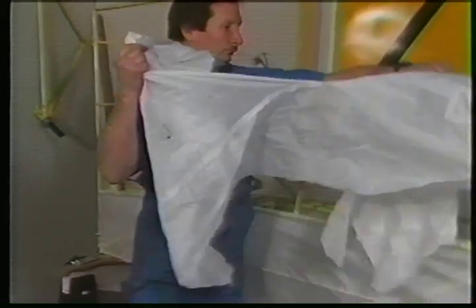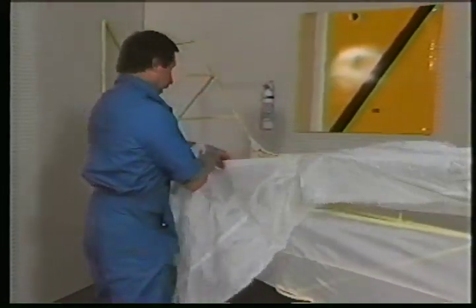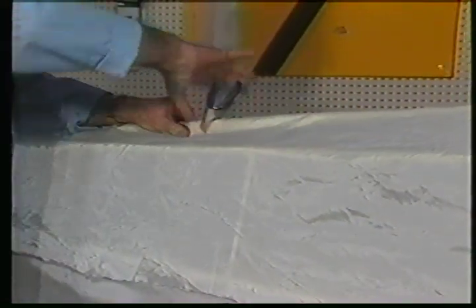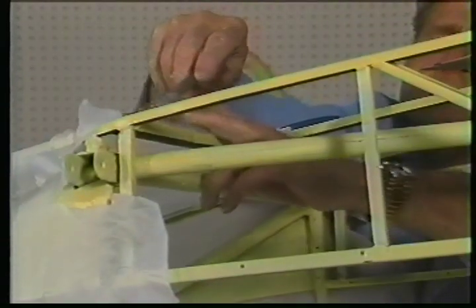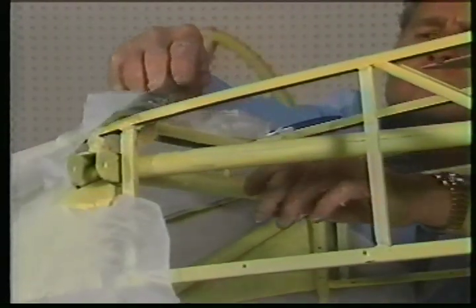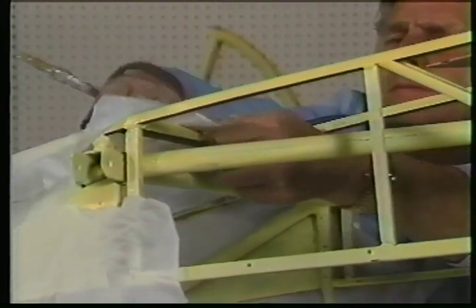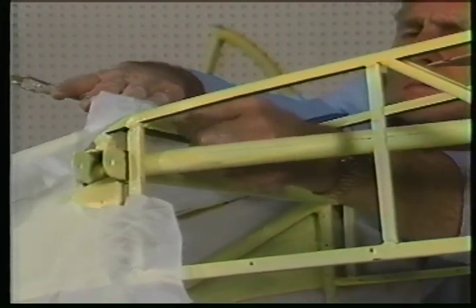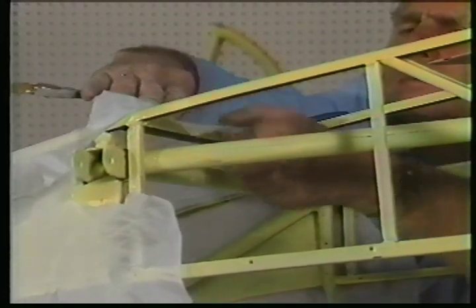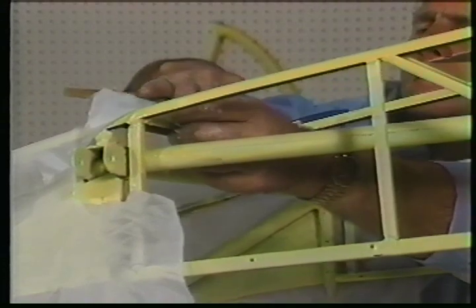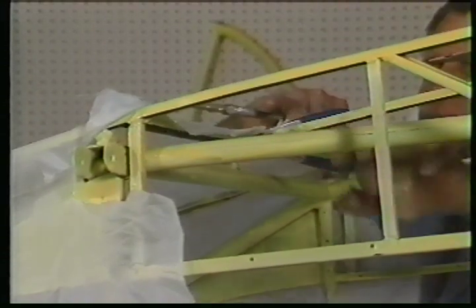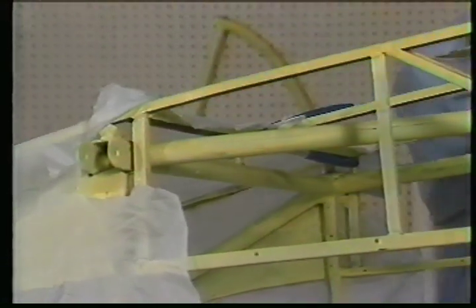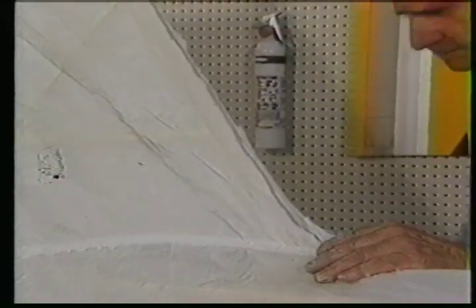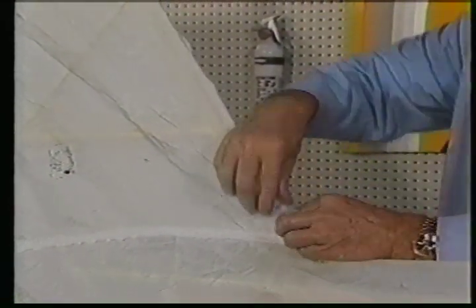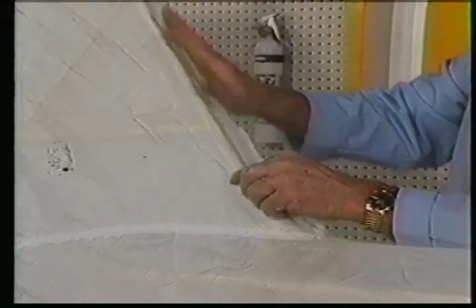After the machine sewing is completed, the top section is positioned on the fuselage and held in place with spring clamps. Start cementing at the top of the fuselage aft of the skylight with the overhang long enough to wrap 270 degrees around the C-section. Special attention should be given to duplicating the original manufacturer's technique of attaching the fabric around a skylight on a high-wing cabin aircraft. Next, trim and fit the overlap seam on the front and top of the vertical stabilizer.